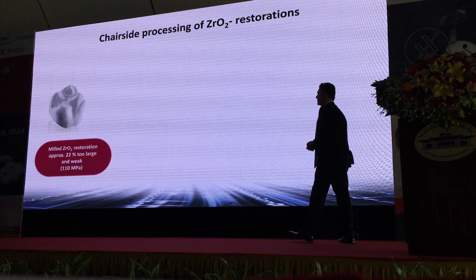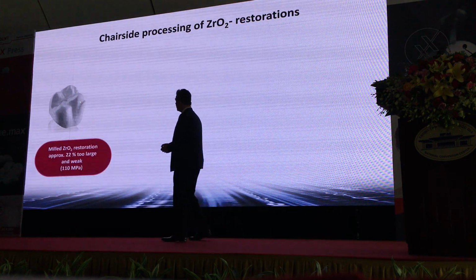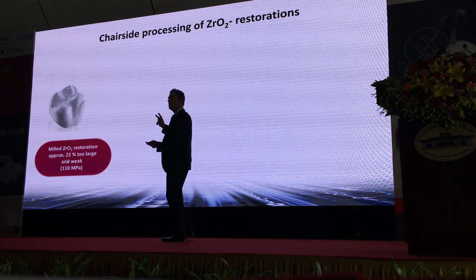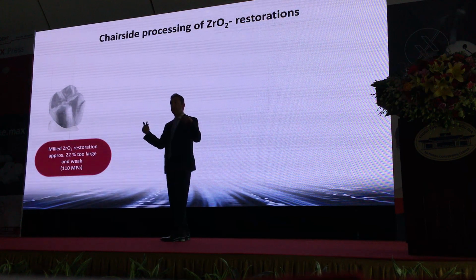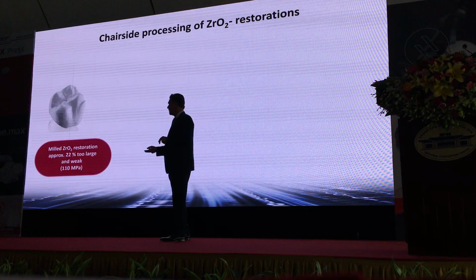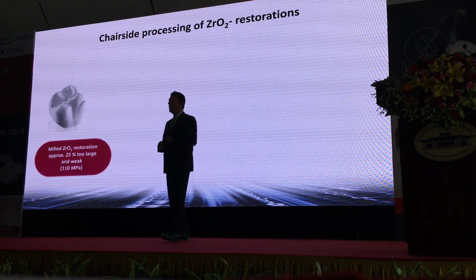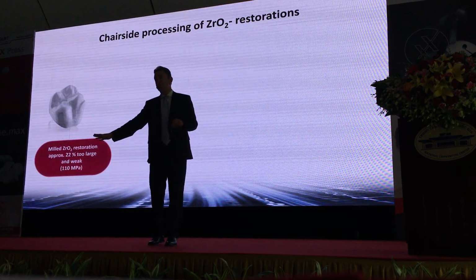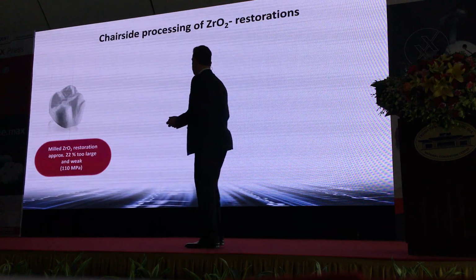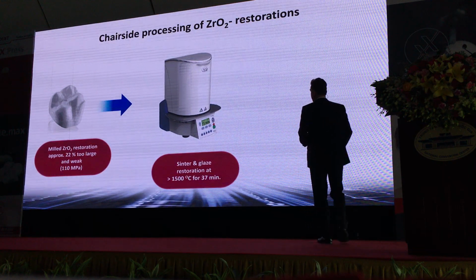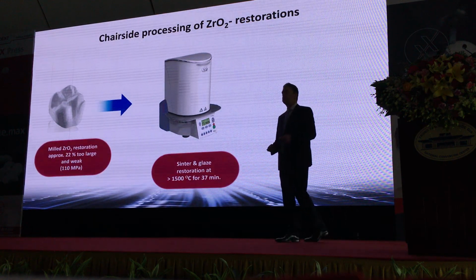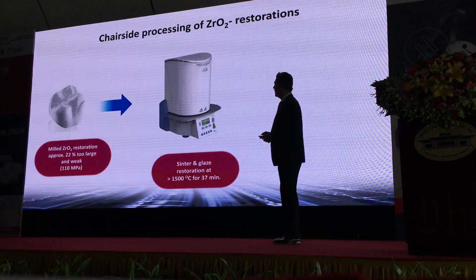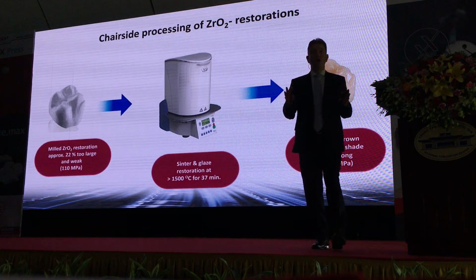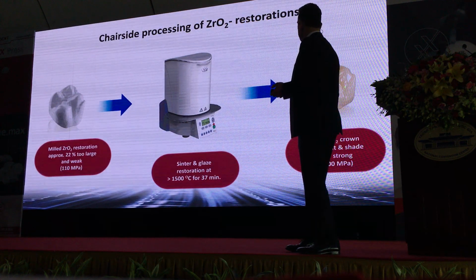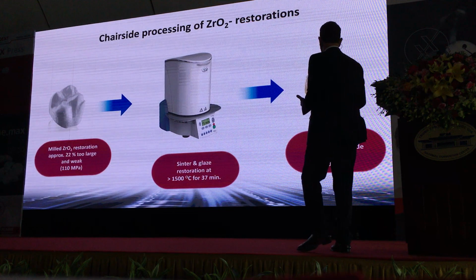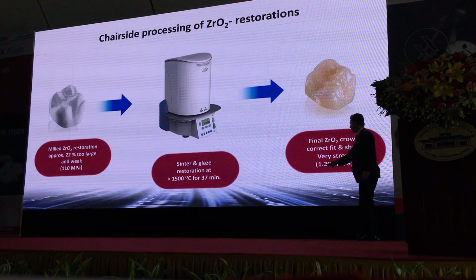All right. So if we mill this restoration, it will be too large. It's about 22% too large, because during the sintering, it will shrink by exactly 22%. In this stage, the crown is very fragile. If you drop it on the floor, it will fracture. It's like chalky, yeah? So now we need to bring this into a sintering furnace, at around 1,500 degrees for a bit more than half an hour. During that stage, this crown becomes very strong. And you can see it's also changing the color. It becomes tooth colored. Yeah? Okay, now we have a final strength of 1,200 megapascals.